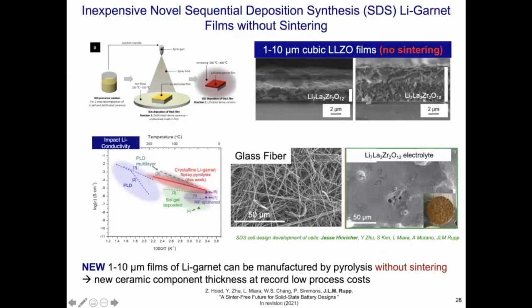And just to show you, and I want to highlight here also some work of Jesse Hinrichs in my group, and also where Andrea Murano is a big part of, this can not only be used later to be coated on a dense substrate, but you can also use, for instance, a porous substrate. So I have here, for instance, a little glass fiber that I just hold here in the camera, and you can use it to even coat glass fibers dense and crack-free, more or less, in really gaining some first coatings, because the capillary forces of the droplets coming down will actually lead to a densification of the film.